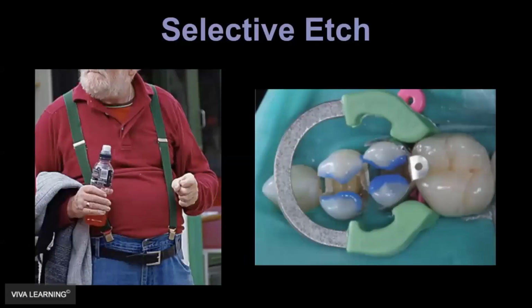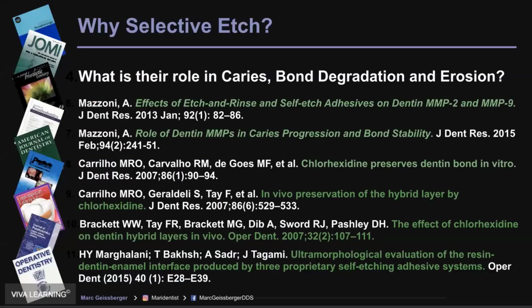No postoperative sensitivity. Now, why do I mention selective etch? Because in a lot of clinical situations, if you're using a self-etcher, you may see after several years that the enamel margin begins to break down if you used it in the self-etch mode alone. Your dentin bond will be great, but your enamel bond can be challenged. Why? Some of these self-etchers don't quite etch enamel as well as I'd like. So what I do is selective etch. Put the blue gel on the enamel surface and then go ahead and use the product as indicated on the dentin.